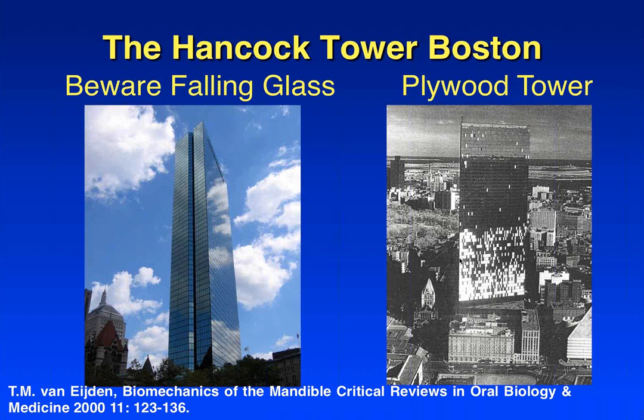But what they found out was that above a certain wind speed, the tower starts to move enough so that these windows are flexing, and what happened was that they had a stiff encasement on the window and the structure, using a very stiff bonding agent between the window and the structure. So what they did is they changed the way the windows were placed and used a little bit of a resilient bonding agent, and that solved all the problems. So now we can walk by the John Hancock Tower without having to look up and worry about a window crashing on our head.